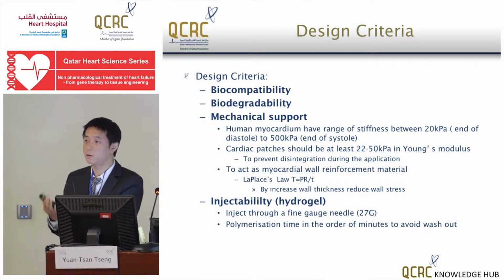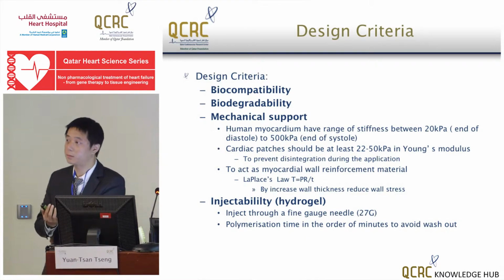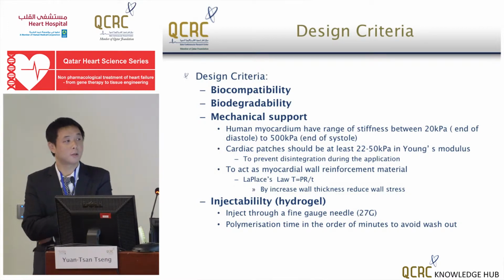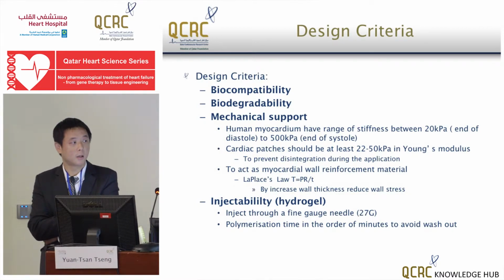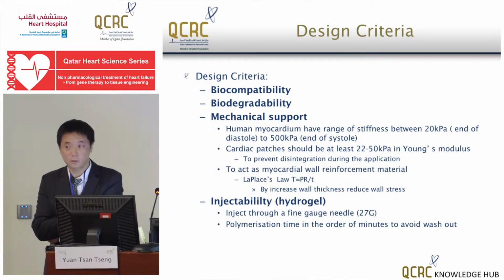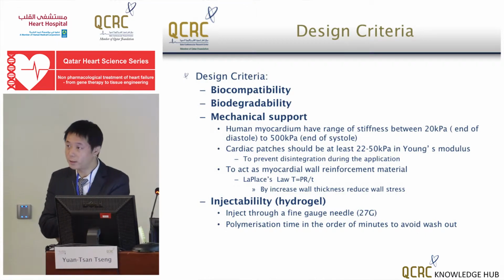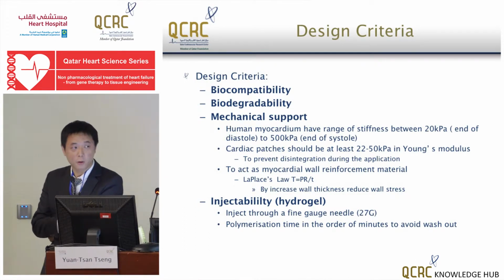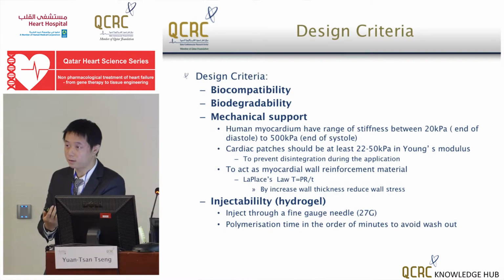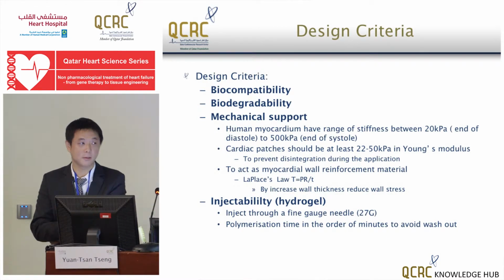And in terms of hydrogel application where injectable biomaterials, you need to consider things like whether the gel is able to go through the needles you use for injections, and what the polymerization time from the solution to gel is. The timing has to be right so that you can actually inject the materials, but at the same time it has to polymerize in time so it doesn't get washed out.